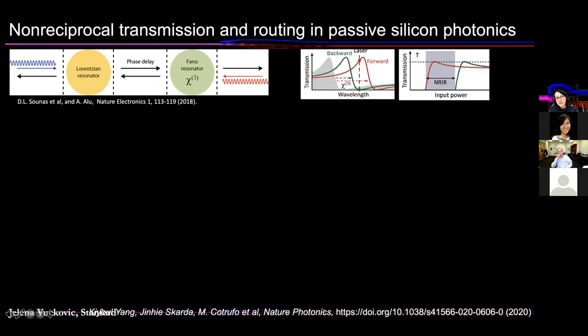So the idea here is from Andrea Alù's group, very simple. He proposed, and they also demonstrated in a microwave circuit a few years ago, that if you have a cascade of two resonators with Lorentzian line shape and Fano resonator line shape, like the one on the right, with some precisely controlled phase delay between them, and the Fano resonator has nonlinearity, this simple configuration could be used to achieve non-reciprocal transmission. And simply you achieve that by controlling coupling to the nonlinear Fano resonator.